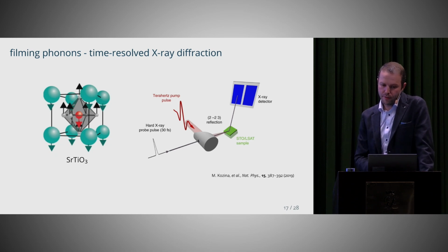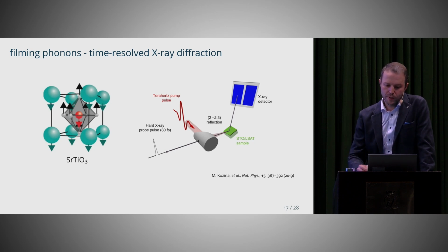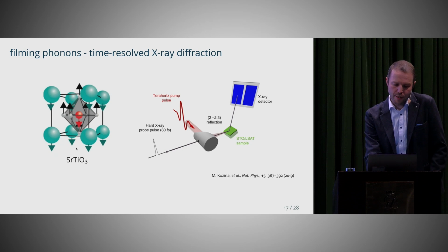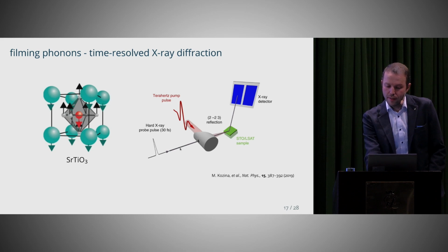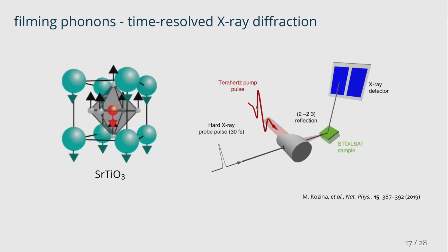There are experiments, and this is an example from the SLAC facility in Stanford, where an experimental group studied the lattice vibration of one specific material called strontium titanate. That's a so-called perovskite material. What they do is the following. They use two different laser beams. One is a terahertz pulse, on the order of 10 to the minus 12 seconds, which acts on this lattice vibration and excites the lattice. Then they have a second laser, a hard X-ray laser pulse. That is the probe pulse, where they measure a scattering, basically standard diffraction scattering for the crystal structure.